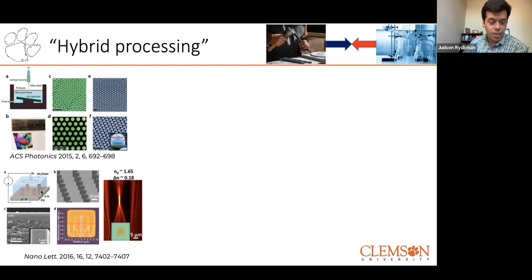So it's put in an electrochemical cell in the presence of HF, apply a current, and as you change the current density as a function of time, you can actually program in the porosity and therefore program in the refractive index. So they've achieved these programmable gradient refractive index micro pillars, and they have some interesting optical properties and lensing effects and birefringence properties as well. So this is a really nice example of combining top-down and bottom-up processes. Again, both of these end up with just silicon, but structured in different ways.